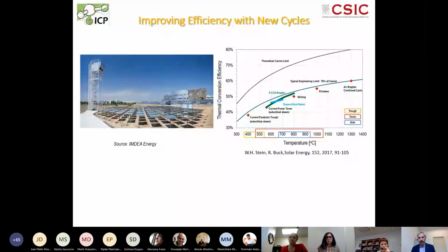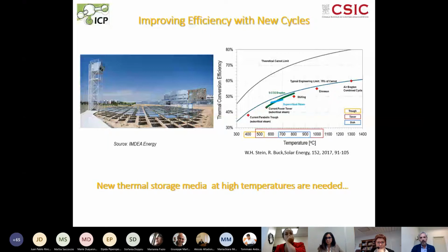Okay, what is going to happen in the future? Well, there is a lot of investigation in new thermodynamic cycles that are going to operate at higher temperature. The reason for that is that, due to the Carnot limits, if we increase the temperature, we increase the efficiency, so we can even get closer to 60% of thermal conversion efficiency. That is huge efficiency. But for that, we need to use a high temperature. So right now, we are centered around 600, and in the future, using different thermodynamic cycles, we'll be able to go higher than 1,000. And for that, as I told you, we cannot use the solar salt, so we need additional materials for storing the energy. So that's the reason there is a lot of research at this moment regarding the materials